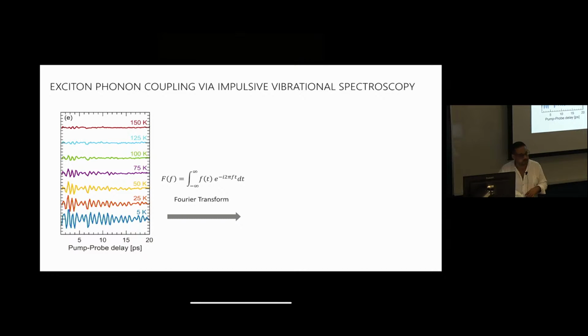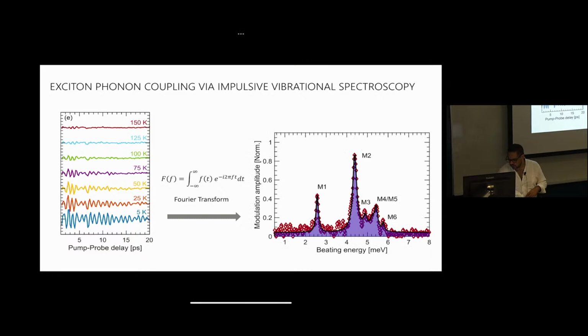You can Fourier transform it, and this is basically a resonance Raman spectrum. And so this resonance Raman spectrum is decomposed into various modes that have a relative intensity, and this is just a labeling, M1, M2, M3, M4, and so on. And so the intensity of these modes tells us there's a phonon that couples to the photocarrier, and the degree of coupling is represented by the amplitude of this. A very strongly coupled phonon will have very high amplitude.